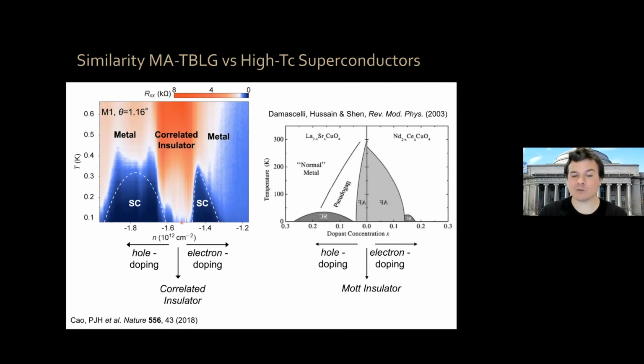Here we have, at 2 holes per Moiré unit cell, a correlated insulator. You add holes and you have a superconducting dome. You add electrons, you have another superconducting dome. Now, a big difference between these 2 systems is that this is a theoretical phase diagram, okay?